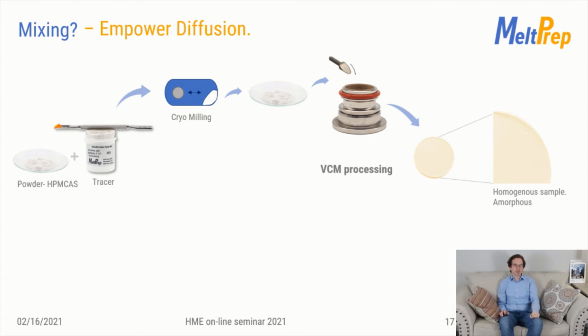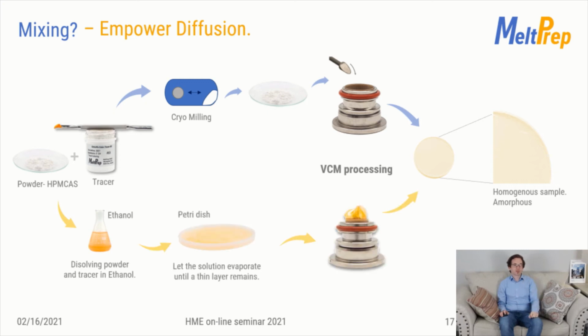Another option to milling is solvent casting. We dissolve the mixture in a suitable solvent and let the solution evaporate. Take the remaining film off the petri dish and put it into a VCM tool. It will also shape into a completely homogeneous disc, which is extrusion-like and suitable for further investigations.